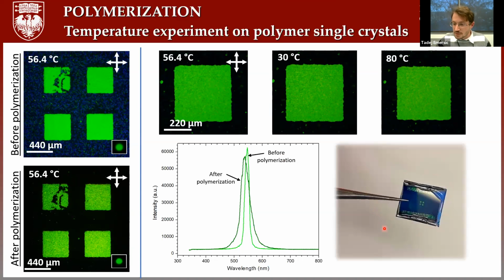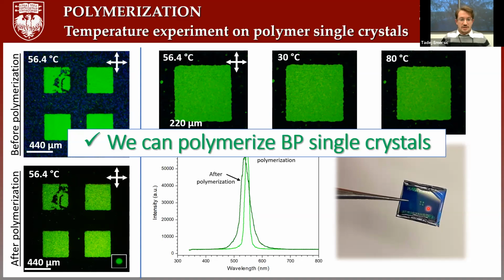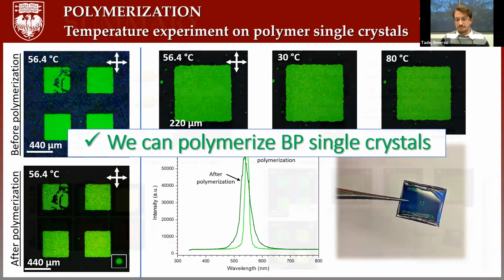This is just a photo taken by phone. And here we can very nicely see the liquid crystal cell, or liquid crystal chamber. And here we can see very nicely these four squares, this is under the microscope, but this is just by the camera, we can very nicely see by eye what they look like. So we can also polymerize blue phase single crystals, right? So not just form single crystals with different blue phases, we can also freeze them.